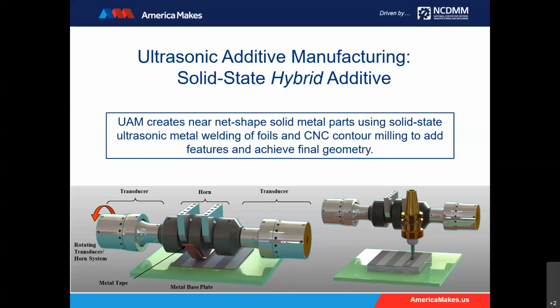So a little bit about how we accomplish this. We have, again, a weld head. We also refer to that as a horn. It's an acoustically tuned device. On either side of that, we have piezoelectric ceramics, and we put a sinusoidal wave electrical signal into those transducers, and they vibrate the entire structure left to right on the order of about 30 to 40 microns. So that horn that you see in the left-hand picture is moving left to right 20,000 times a second at about 30, 40 microns. As it's vibrating, it's rolling forward out of the page, rolling over these foils and bonding them down to the surface. And then, of course, we can come in at any time with the CNC mill to affect geometry. So in effect, we're printing near net shape and then milling to get the exact shape that we're looking for.